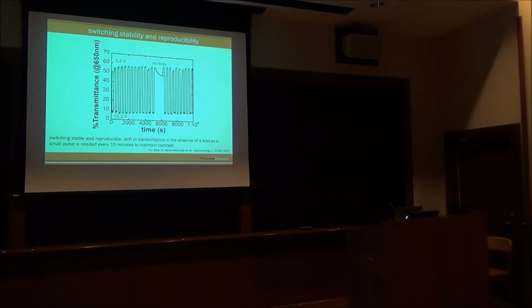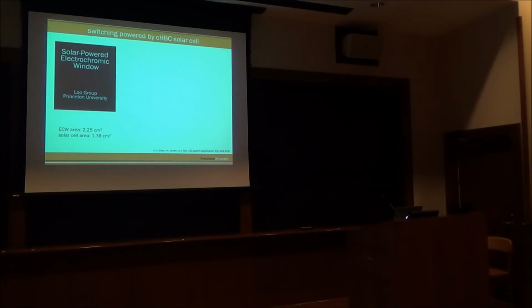This is to show that the window can be operated stably, and so you can go back and forth between the bleach state and the colored state. And so with electrochromic materials, what's nice is to access that oxidation state, you need a pulse. Okay? A pulse gets you there. When you have no bias, it basically slowly bleaches. And so we determined that basically every 15 minutes, you need to pulse it a little bit so it brings it back to the original oxidation state to maintain the color. But as long as you do that, you can maintain the transmittance and you can maintain the opaqueness at where you'd like it to be.